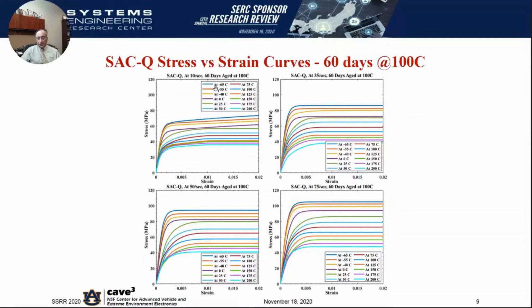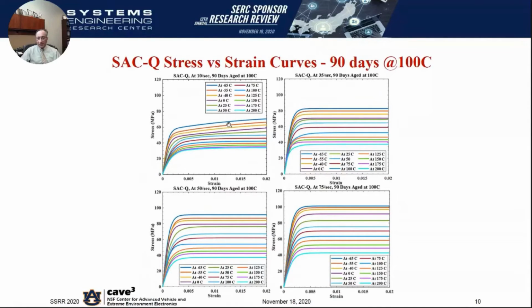And here, the data has been taken over the entire temperature range that I talked about at the beginning of the presentation, which is from -65 to +200 degrees centigrade. And so you can actually see a similar effect exists for SAC-Q as well, where as I increase the operating temperature, my ultimate tensile strength is dropping. And as I increase the strain rate, my UTS is increasing, and so is my effective stiffness. And again, if I go from 60 days to 90 days, I can actually see the curves migrate downwards.